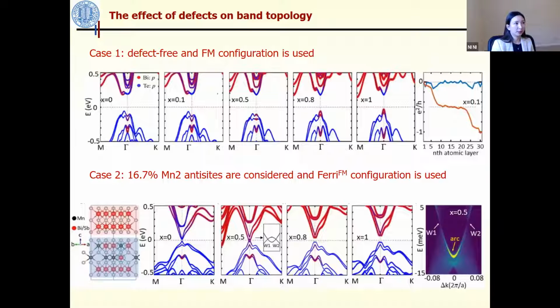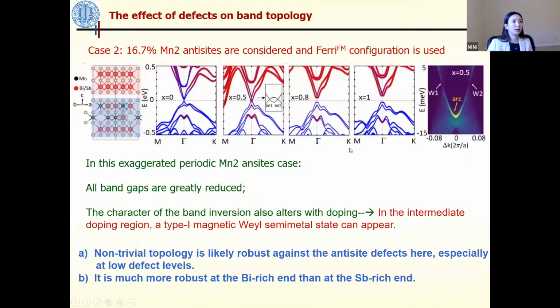But we have defects, right? So next, to simplify the problem, we assumed 16.7% of manganese-2 antisites, and we used the ferromagnetic configuration. And now the band structure has changed much, right?